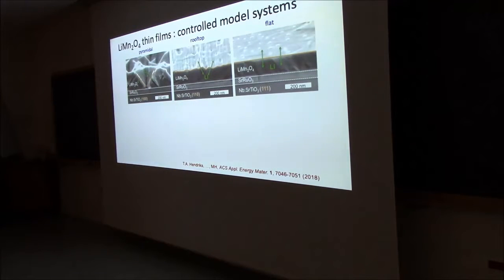But you can see I'm forming pyramids. And these pyramids sometimes are truncated, but they really clearly form pyramids. And that's because the 111 crystal facet is the energetically most favorable one for spinels. So the moment I grow it on 110, you see I have these kind of rooftops. And if I take a 111 orientation, it's very flat. So if you put this in a schematic picture, you can easily come up with this to say, okay, this had to happen if 111 is the most stable one. And in this pyramid structure, you can see some of those pyramids are truncated, so you have a 100 top as well, which is sometimes happening.